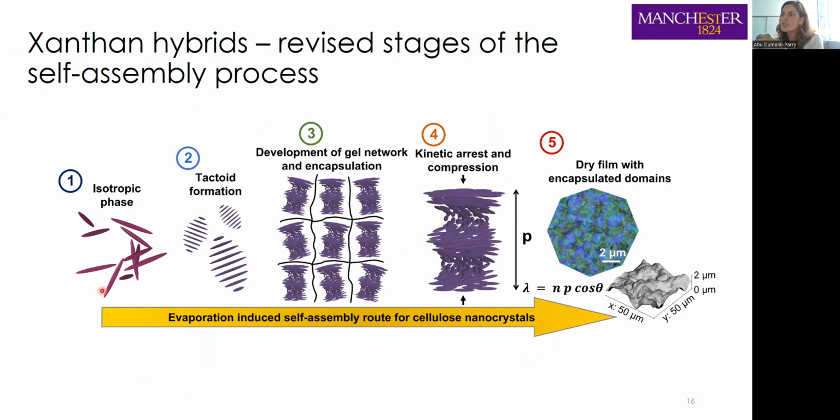So we put another polysaccharide into the system. Xanthan gum is a microbial polysaccharide from Xanthomonas campestris, and it is produced by fermentation. Upon thermal annealing, xanthan can go through a gelation process spontaneously itself as well.